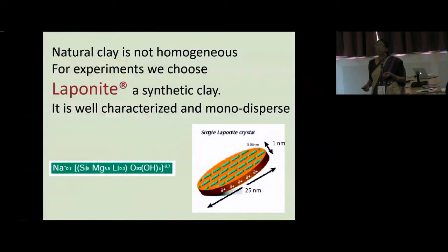Now, for our experiments, we do not use natural clay because that is not well characterized. We use a synthetic clay, which is called laponite, and it is quite mono-disperse. The particles are very small, nano-sized, as you can see here. And this is the chemical composition. It is all very well known and quite well studied. So what happens when we dry a paste of laponite?